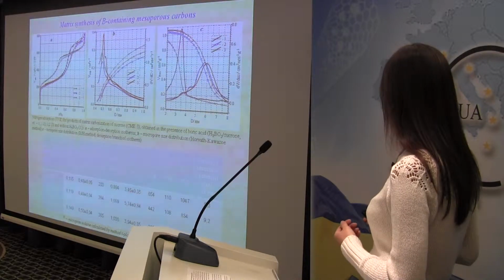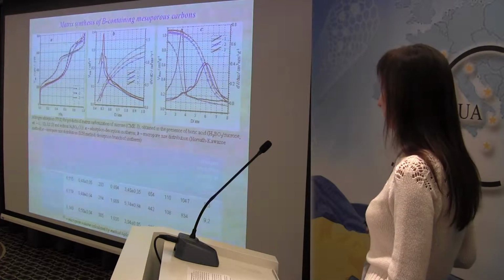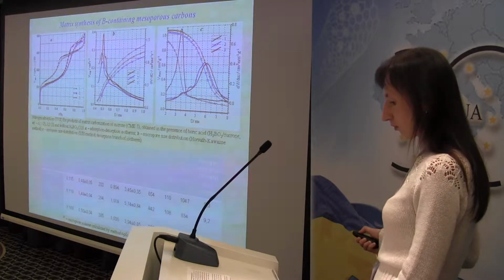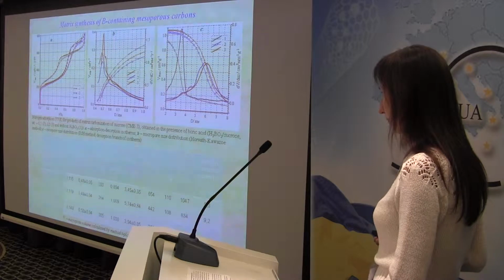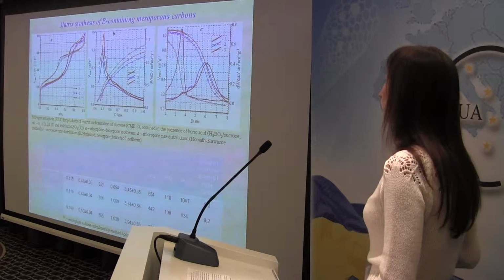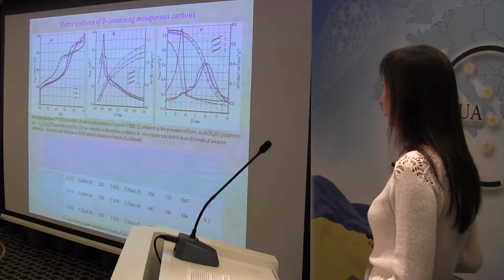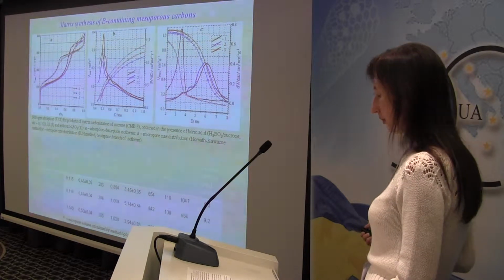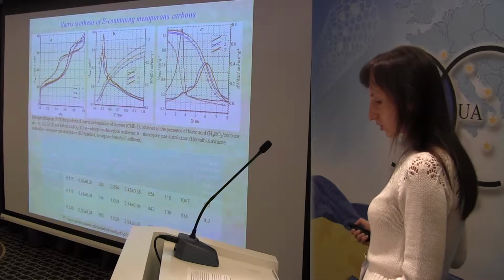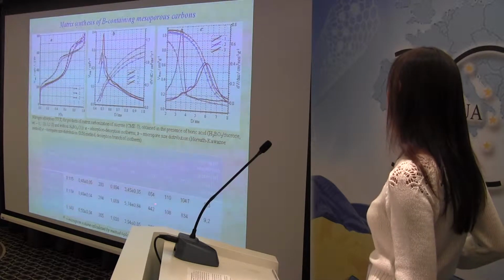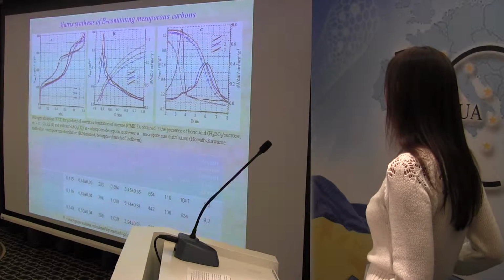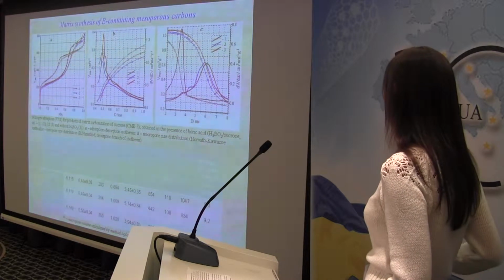As a result of matrix carbonization of sucrose in mesoporous molecular sieves of SBA-15 type, in the presence of sulfuric acid catalyst and boric acid modifier, with subsequent dissolution of the silica matrix, mild activation of carbonization of sucrose is observed, which leads to formation of mesoporous carbon materials and compaction of the carbon phase in mesopores, and thus a significant increase in mesopore diameter, volume, and specific surface area compared with the traditional process.